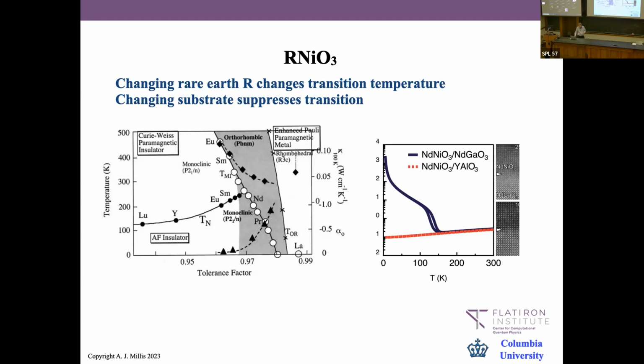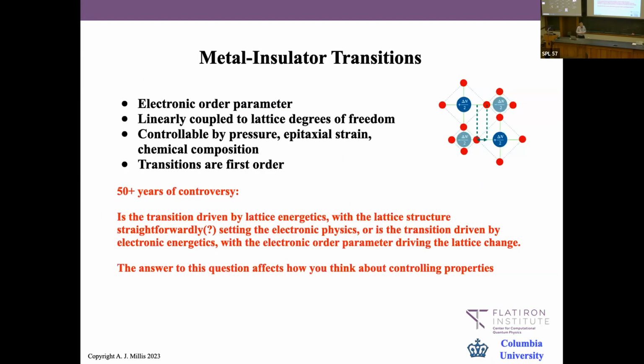Okay, so to summarize, there's this whole family of metal insulator transitions in which there's some kind of electronic order parameter, a little bit different for the different cases, coupled to a lattice degree of freedom, typically linearly. This coupled system has a transition between two quite different states, which has sometimes useful properties. This transition can be strongly controlled by pressure, strain, chemical composition, and so on.